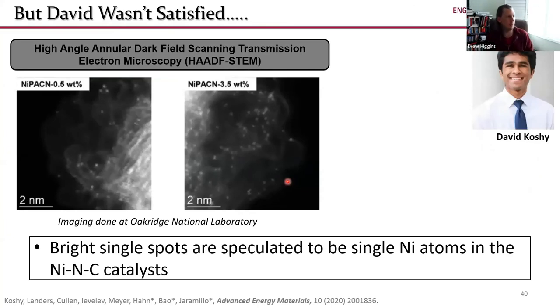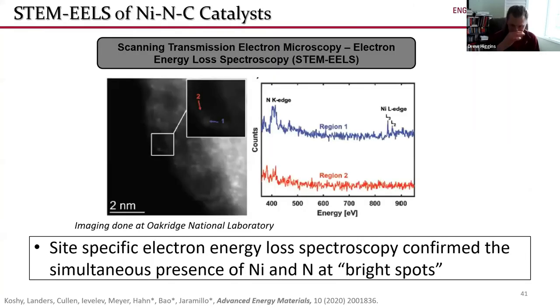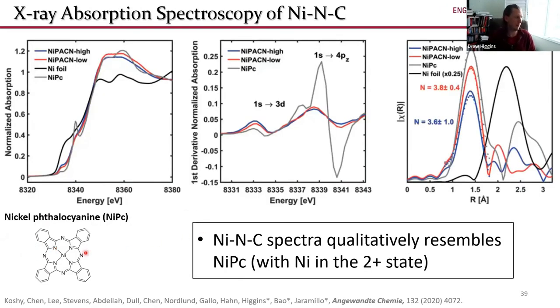But David wasn't quite satisfied. So he took these materials to Oak Ridge National Laboratory, where they had some very nice electron microscopy facilities, and he did scanning transmission electron microscopy measurements with related EELS spectroscopy. And he saw these bright spots that said, okay, you've got these higher Z number atoms present in your materials. But then he also did the correlated spectroscopy to figure out what the identity of those atoms was. And what he did find is that those atoms were largely nickel coordinated to nitrogen within this graphitic structure. He also did some time of flight secondary ion mass spectroscopy measurements when he was at Oak Ridge National Lab. And essentially all of that, once again, pointed towards the presence of this nickel phthalocyanine-like structure in these materials.